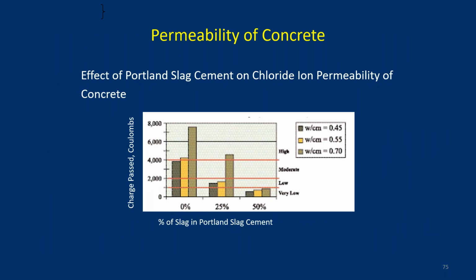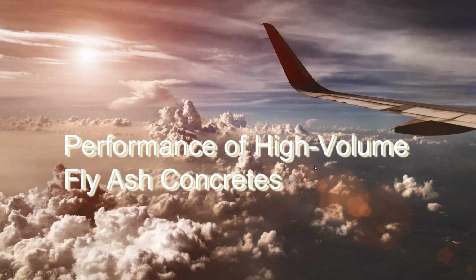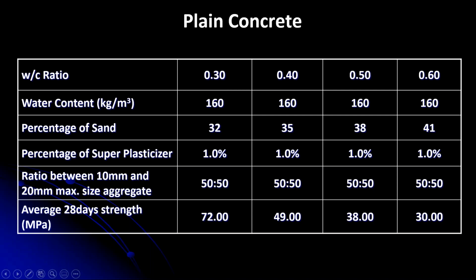And so this is another. So you can see this is 25% slag and 50% slag. The higher the percent of slag, the lesser the number of coulombs, and for different water cement ratios and all those things. Okay, we did some work in CBRI.